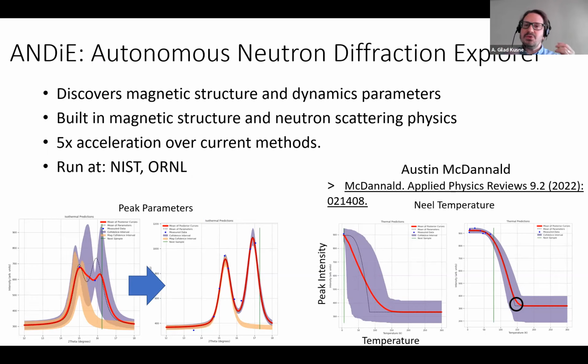So what we did was, since we're using neutron scattering and we're studying a magnetic material, we encoded magnetic physics and we encoded neutron scattering physics into the machine learning. And so then we got a dramatic acceleration, 5x acceleration in honing in on these properties. In this case, the system was able to select which 2 theta angle is the most optimal to measure next, and also what temperature is the most interesting to investigate next for honing in on the Neel temperature. So the autonomous system was controlling 2 things: the angle of the detector and also the temperature of the sample.